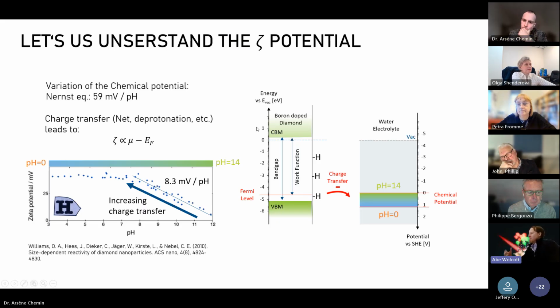What's interesting about the current graphic on the right-hand side is that for a boron doped diamond, which is a p-type semiconductor, the Fermi level is extremely low. In the case of any of our detonation diamond or HPHT, those are all nitrogen doped, and therefore it's an n-type semiconductor. So we're really going to have to bring that Fermi level up. So it's interesting if we could have the same mechanism even regardless of the Fermi level. And I don't think there's any boron doped nanocrystals out there. No, all of them are nitrogen doped.